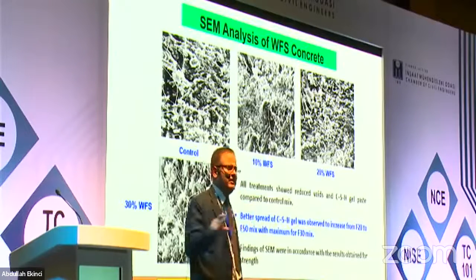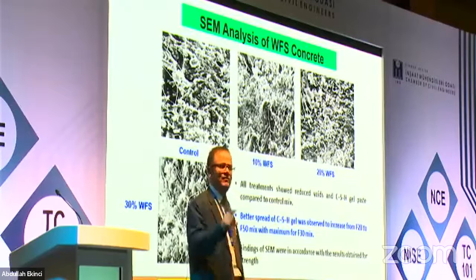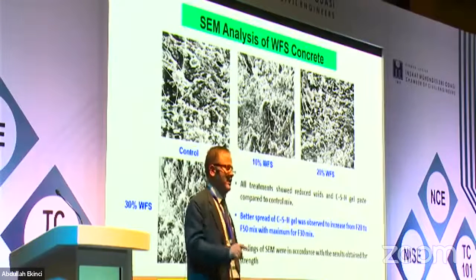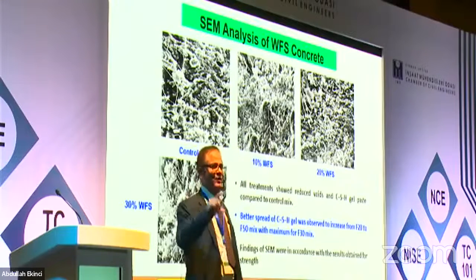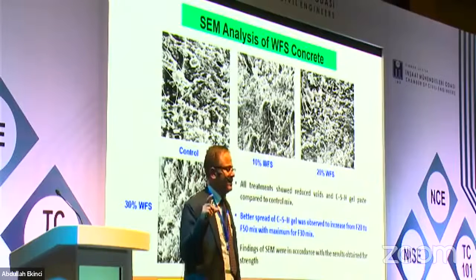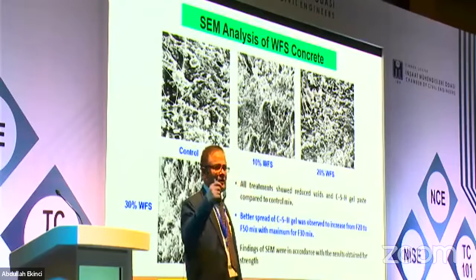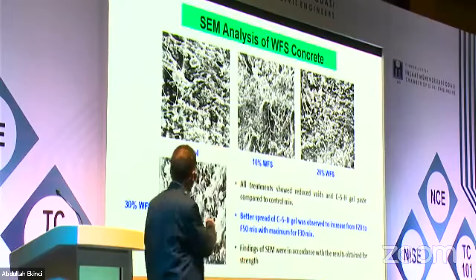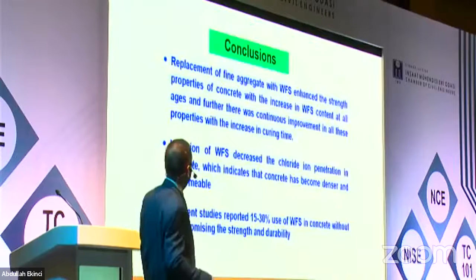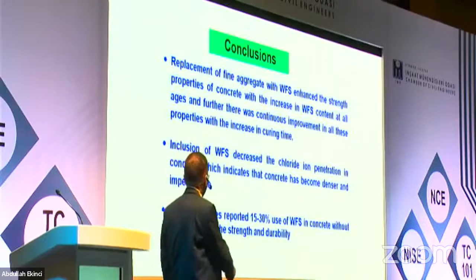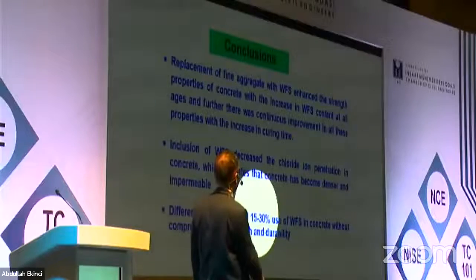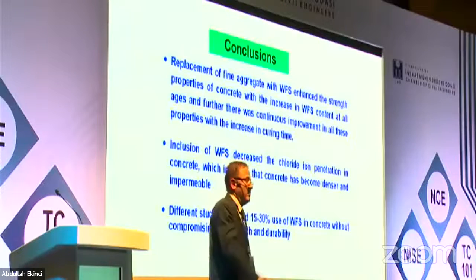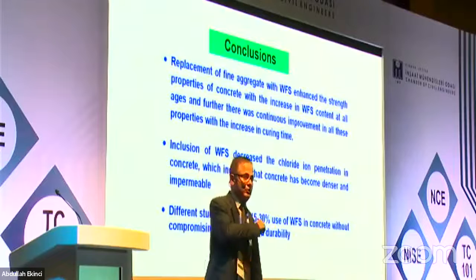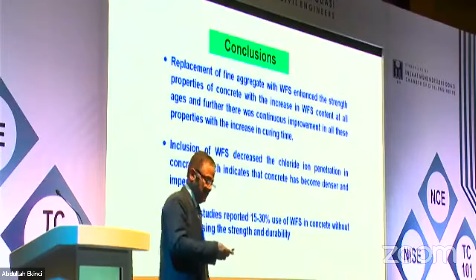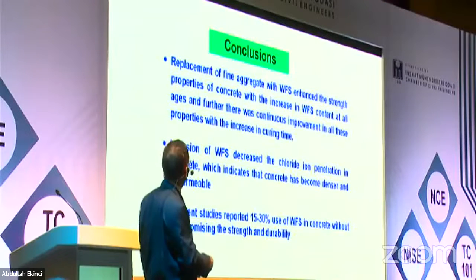Otherwise, everybody does fresh properties, everybody does strength properties, everybody does durability properties. So what is new in your research? If you do this leachate part, your publication will have a better value. Similar to the conclusions here, you can easily use 15 to 30% in structural concrete. If you want to use higher than that, the Jamal Khatib reference is more than enough.